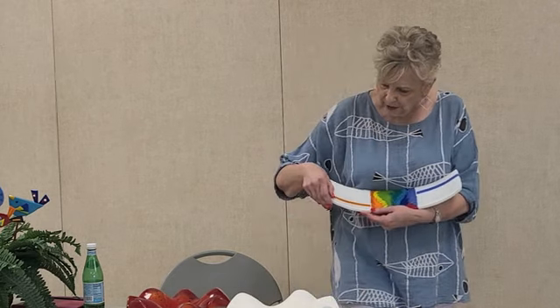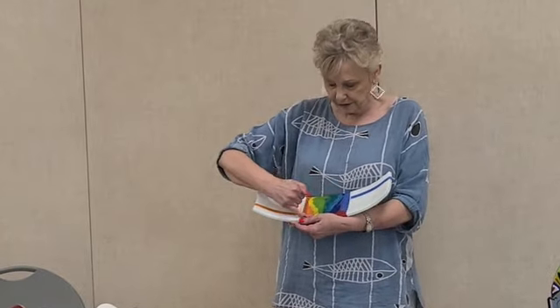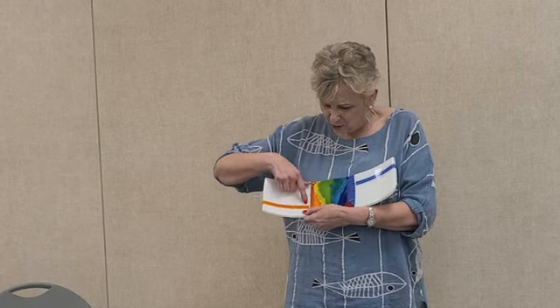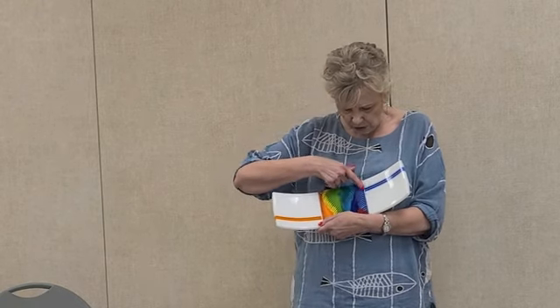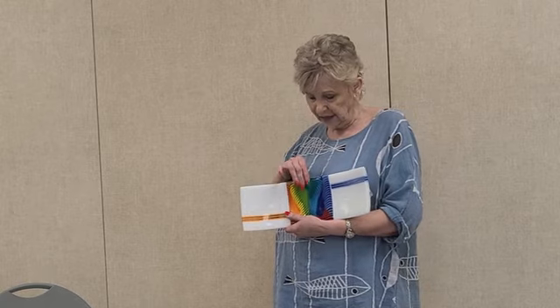And then I had this square of glass that I didn't know what to do with. And so I put it in between layers of white glass with stripes and tried to line the stripes up as best I could with the way the flare out over here is. And it's really interesting in that this is a three layer piece. So I had to dam it, because it wants to be a quarter of an inch, it would have spread out, because I would have started with 3/8 of an inch of glass. So I wanted to keep it 3/8 of an inch because that's how thick this was.